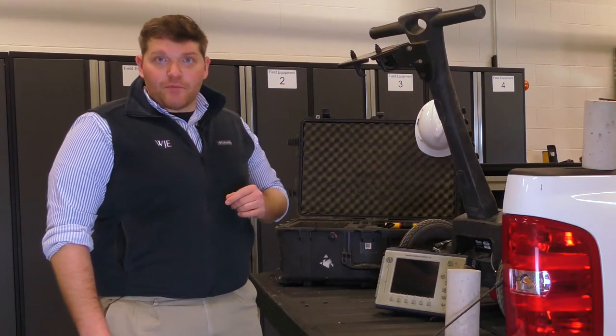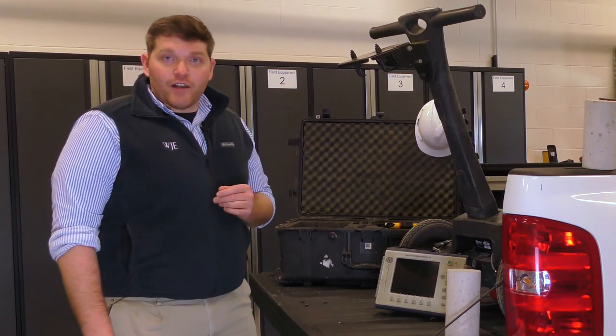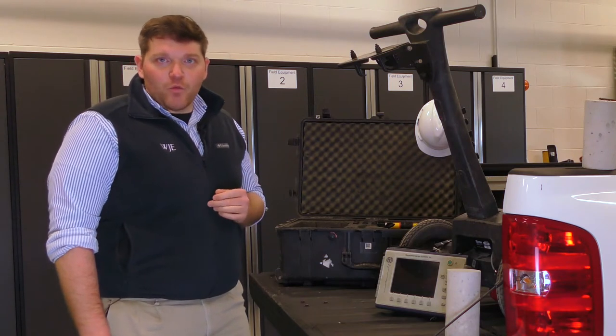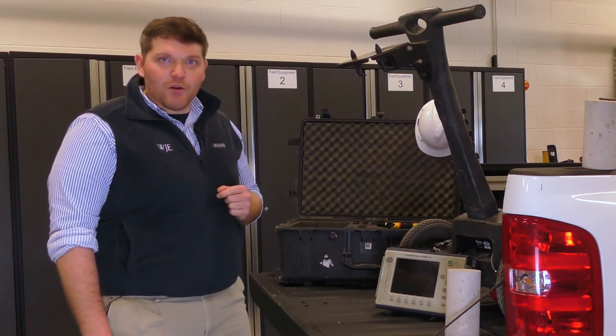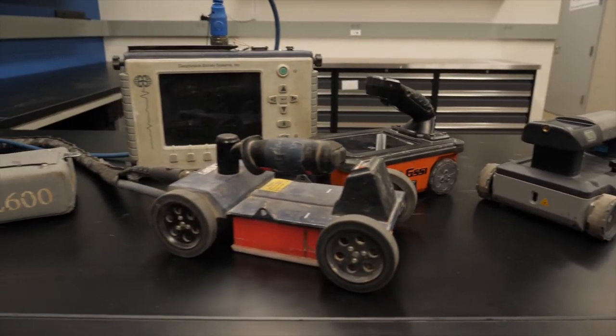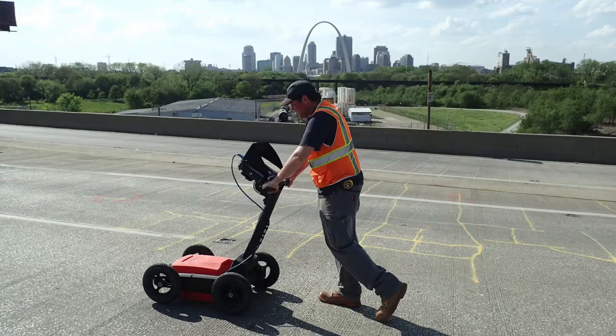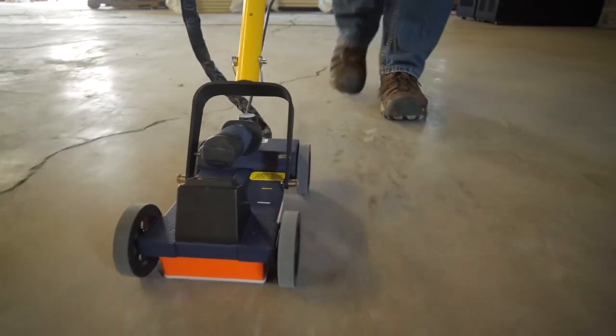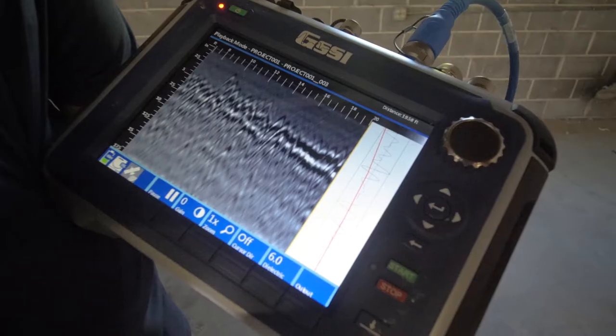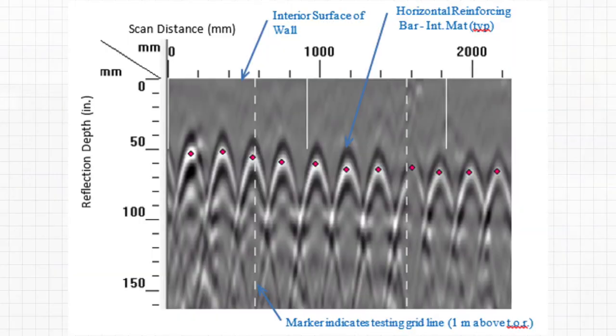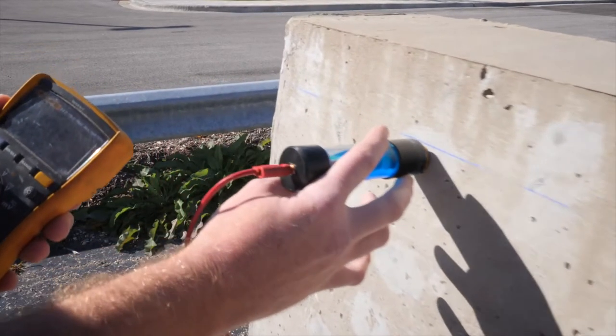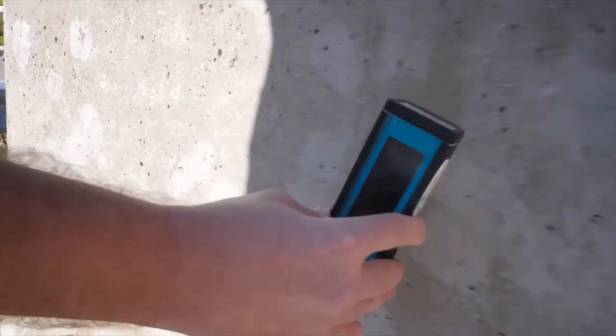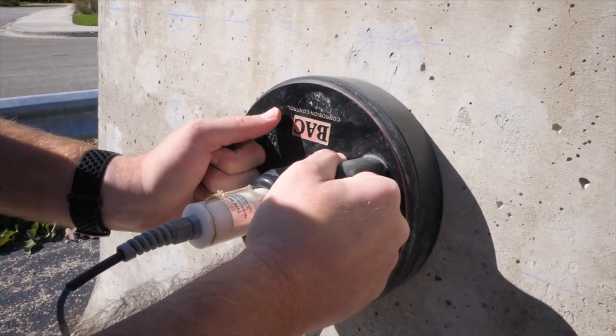In addition to the visual and sounding methods, we'll utilize advanced non-destructive evaluation techniques to further characterize our structure. A very common method we'll utilize to evaluate the as-built conditions is ground penetrating radar, or GPR. GPR can either be a handheld portable antenna or a cart-mounted antenna to allow us to rapidly collect data across a structure. Utilizing GPR we're able to characterize the as-built conditions including reinforcement location as well as reinforcement cover depth. Other non-destructive techniques including corrosion assessment methods such as half cell, surface resistivity, and corrosion rate can be used. Based on the results of our visual surveys, hammer sounding, and non-destructive evaluations, we'll locate material sampling locations on our structure.